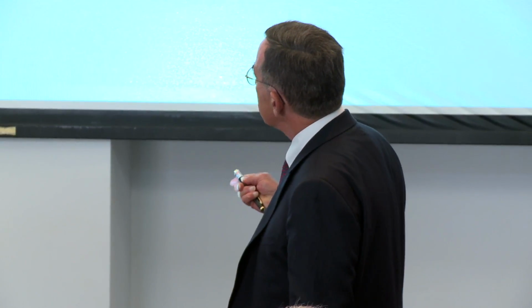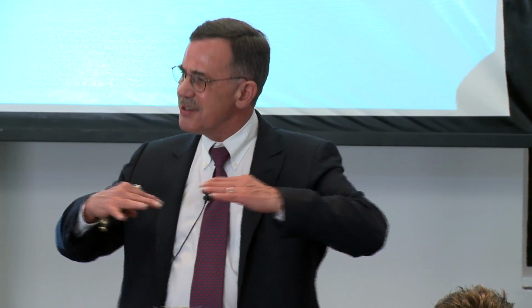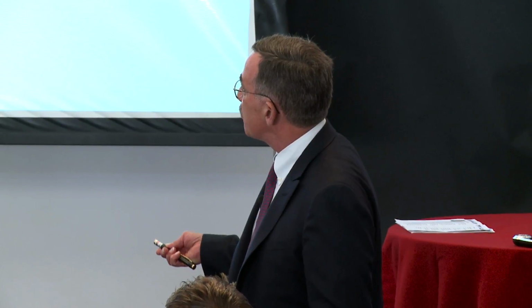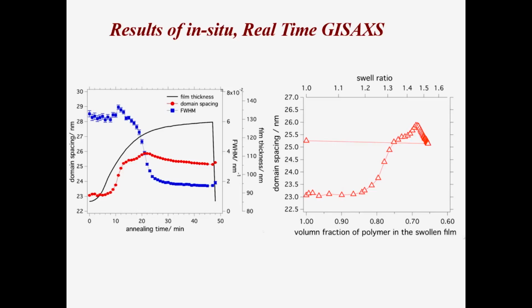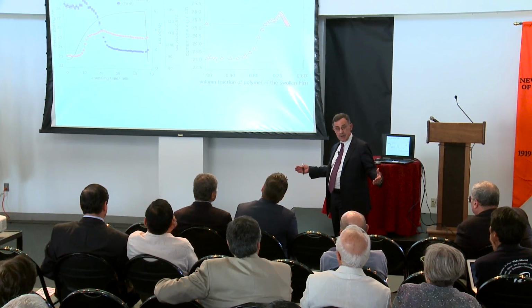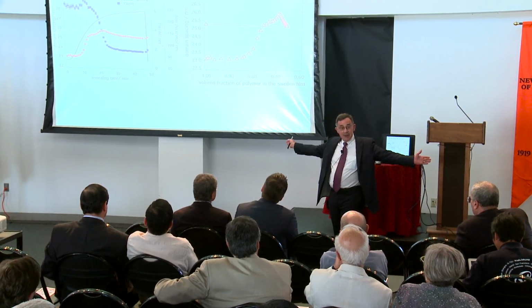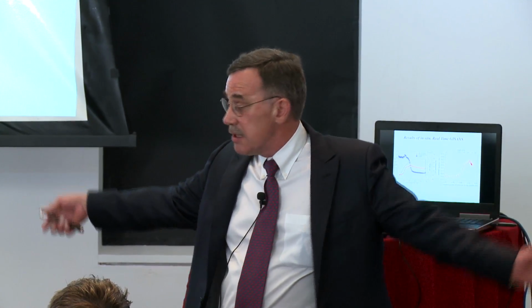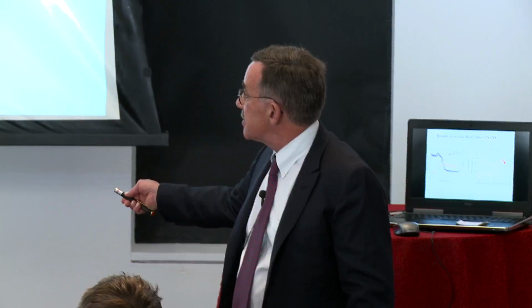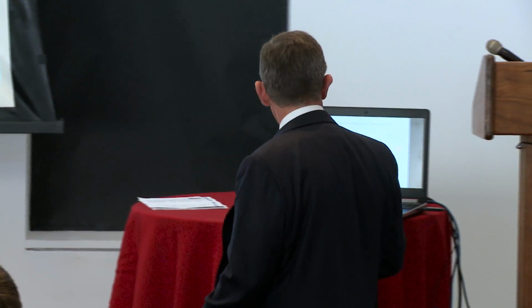What one also finds is that if you look at the full width at half max, this reflection initially starts off as being diffuse, and then it starts to sharpen. And the reason it starts to sharpen is that the lateral ordering is improving. This is a very quick measure of the overall lateral ordering. This is the overall film thickness. And if you think of it, the film thickness is exactly the amount of solvent that's being put in the film. Because as you add solvent, volume increases. If you're on a substrate, you can only get thicker, you can't get fatter, because you can't fall off the substrate. All right? So this tells us the swelling ratio, this tells us the lateral order, and this tells us something about the peak position.